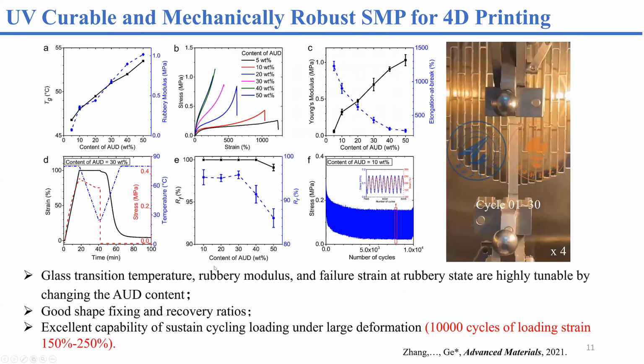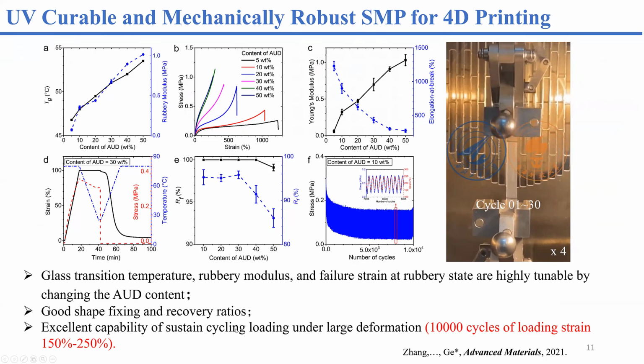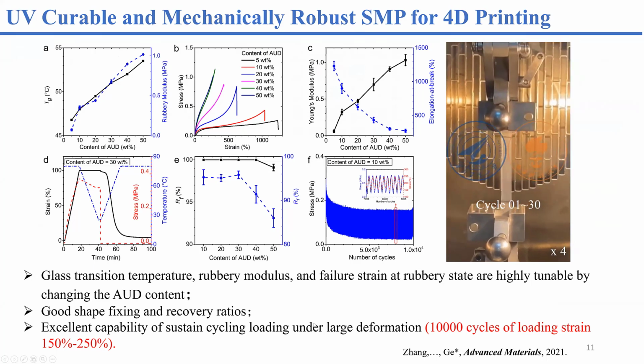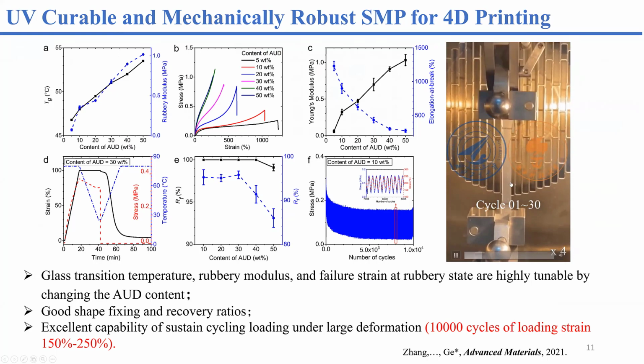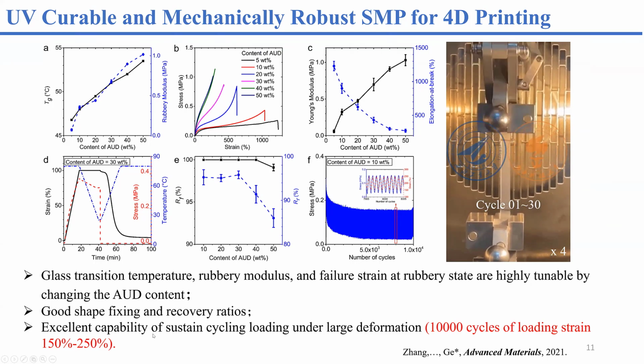And more importantly, we can tune the thermal mechanical properties by simply changing the cross linker. And as I said, it shows good shape fixing and recovery ratio, and more importantly, this material exhibits excellent capability of sustained cyclic loading. So we apply the mechanical load at its rubbery state, from 150% to 250%. The material can sustain more than 10,000 cycles without any failure. So this is an excellent material.